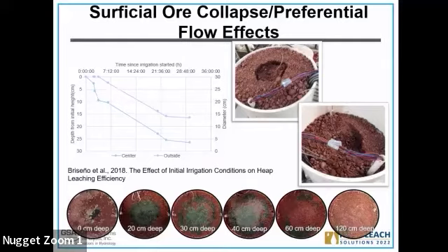This topic will be presented by Mike Mazzarica in tomorrow's session. A little bit by accident, we reversed that. I wish you could see this, so I don't have to cover it again. But what happens is that you load the full irrigation scheme at the start. You can see that in only about 2 hours, the center of the ore sinks down about 10%.